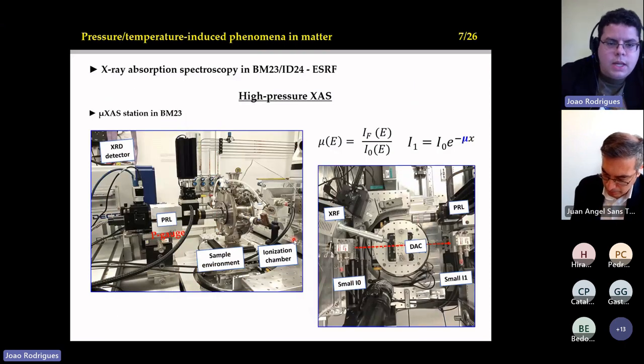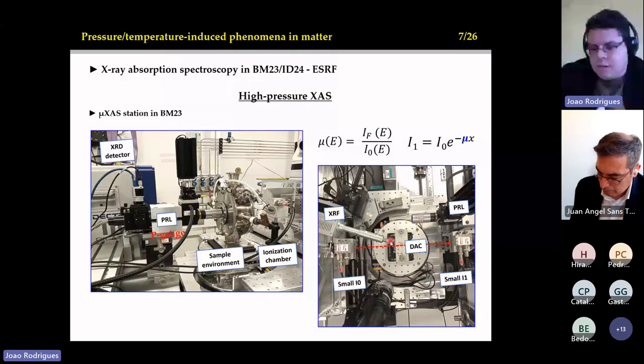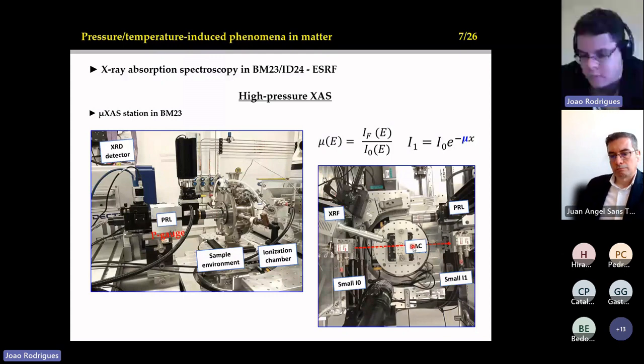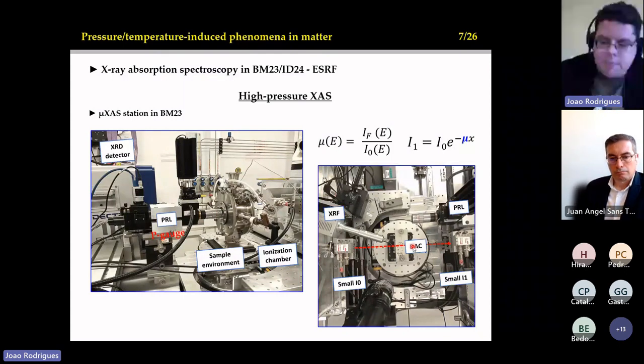Okay. So in the high pressure end station of BM23 ID24 at the ESRF, we basically have this kind of setting. We can put an X-ray detector. We can put also the ruby, which is for measuring the pressure inside the cell. We can change the sample environment. This case was an interesting high temperature cell to measure X-ray absorption under pressure and high temperature. Or you can also mount X-ray fluorescence and do, for example, mappings of very small diluted materials in this beamline.